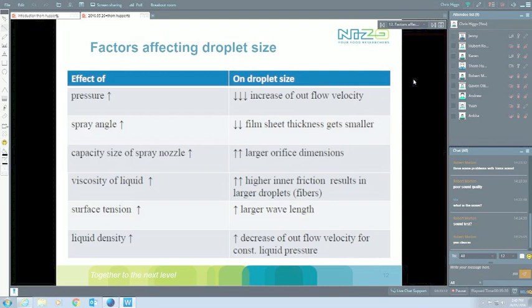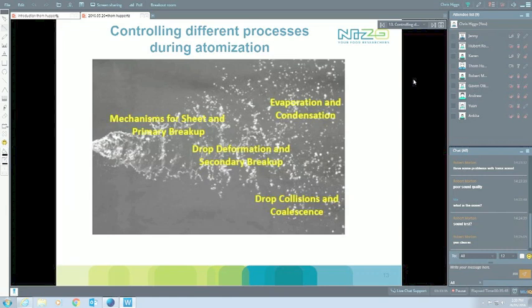Surface tension is in theory one to play with, but in practice there's not a lot you can do there from a milk perspective. And of course the density of the liquid has a big effect as well, but that's really related to your dry matter content and to your viscosity. So what we really see, we concentrate on milk, we put it through a dryer, we put it through an atomizer. And what we basically see is we get our sheet formation, we get a primary breakup, we get droplet formation that can even start breaking up further, so we can have a secondary breakup. And then on the one hand, of course, we can get our evaporation, we can get our actual drying happening, but we need to be wary as well that we can get collisions between particles again, and we can get coalescence, they can start growing again.